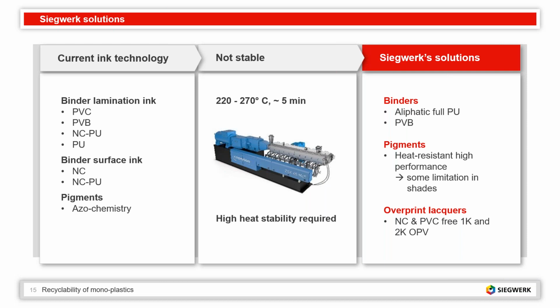And on the right-hand side, you see now how Siegwerk can help overcome these limitations and help you using more suitable inks. When we look at the binders again on the right upper side, there we have to take the thermally stable ones, which is the polyurethane chemistry, preferably the so-called aliphatic ones, but also polyvinyl butyral can be used.